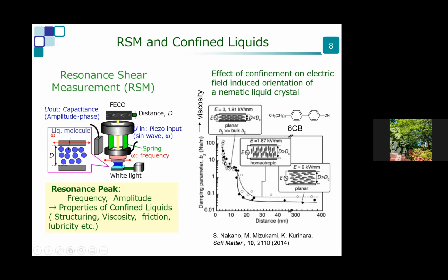Then when we applied an electric field, the orientation of the liquid crystal changed in such a way that viscosity increases for such lateral motion. But at distances below 10 nanometers, the two values started to coincide. That means that the electric field cannot change the orientation of the liquid crystal at such a narrow gap. So this is the first observation of such a confinement effect.